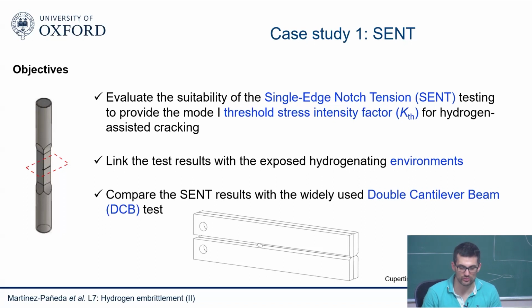So this case study is something that we published last year, and the idea was to evaluate the suitability of the single-edge notch tension samples, and this was more a study related to operations of the oil and gas industry. So it's more what they call sulfide stress cracking, which is still a hydrogen embrittlement phenomenon, but it's a phenomenon that you get in H2S environments. And H2S environments are environments where you have a lot of hydrogen, so it's pretty bad, but at the same time there are other things happening, so it's a bit more complicated.